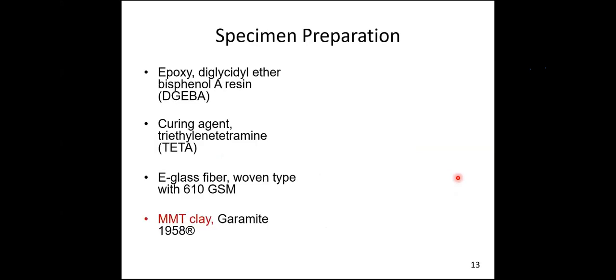So now, how to prepare the composite sample? We need a matrix, so we need a polymer. As we are doing this study for aerospace application, we have chosen a DGEBA resin, that is diglycidyl ether of bisphenol A resin, which is aerospace grade resin, and we used triethylenetetramine as a curing agent, and also we used typical E-glass fiber in order to understand the effect of clay in composites.